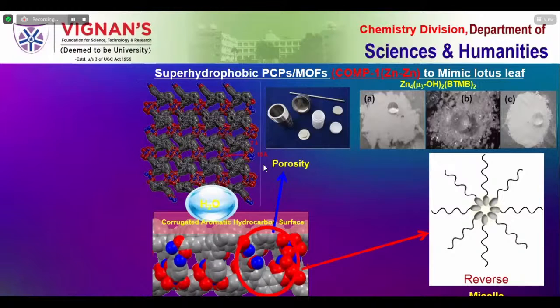So that's the reason why we thought that maybe the corrugation, meaning non-uniformity, and moreover the hydrophobic moiety exposed to the layers, give rise to these super hydrophobic materials. In fact, this is a unique behavior. Earlier, super hydrophobic MOFs were known, but the main problem is they modified the surface using fluorocarbon moieties or lengthy alkyl chains. If we introduce lengthy alkyl chains here, the porosity will be lost. But in this case, without modifying any surfaces, we directly got these super hydrophobic materials. That's the reason why this work was highlighted by Nature one week as a kind of sponge which can repel water.